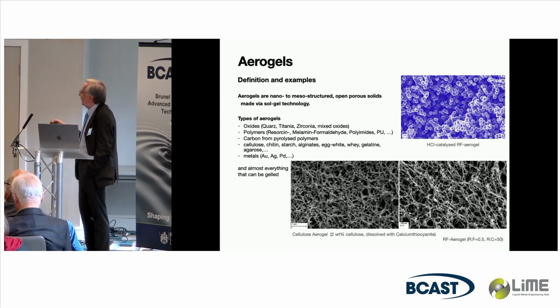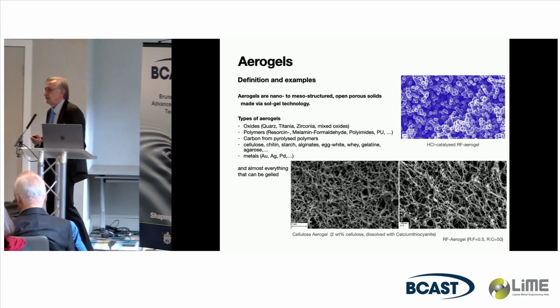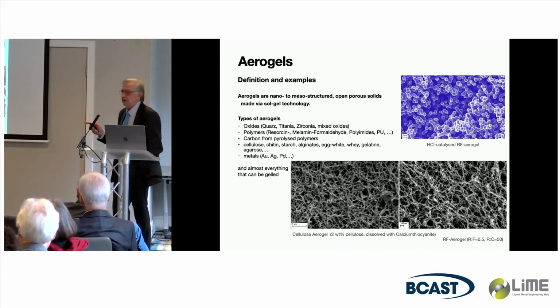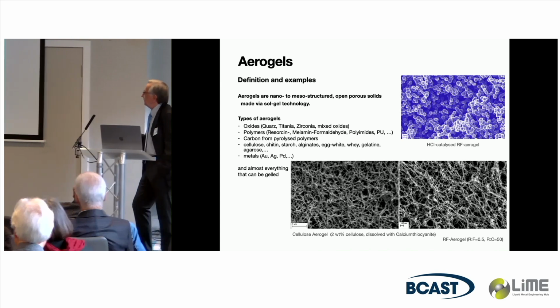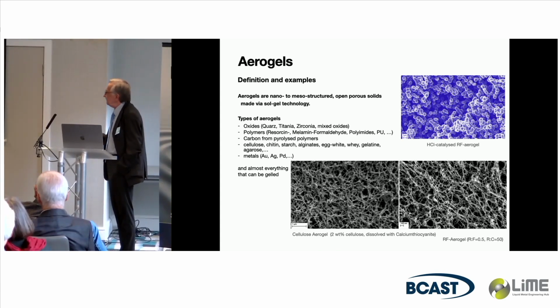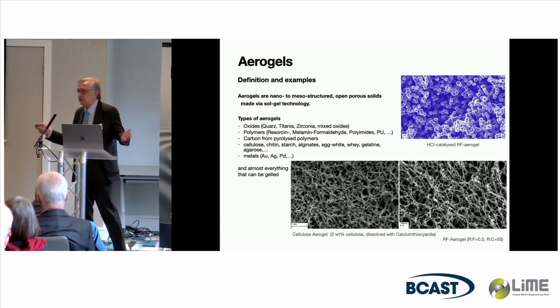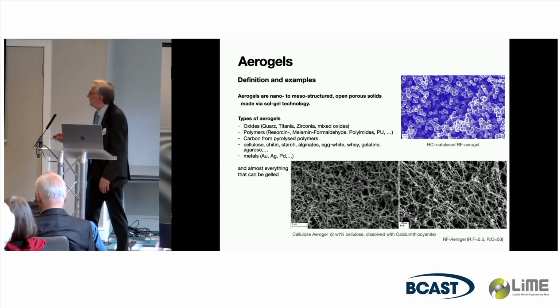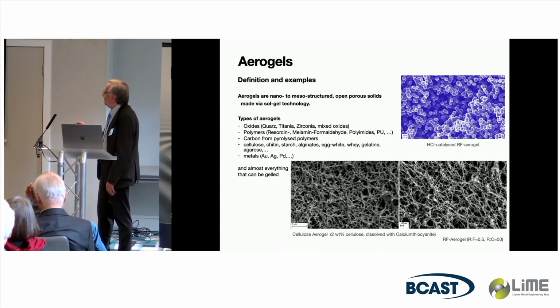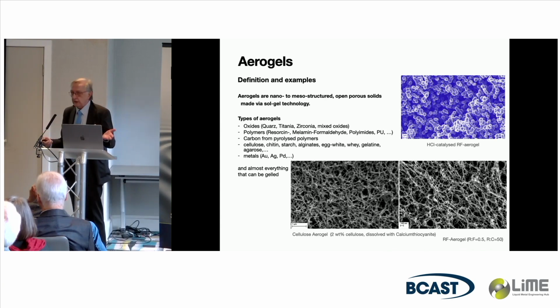Aerogels are open nano to mesoporous structures, open porous solids, always open porous, and they're all made via a sol-gel technology. You can make aerogels from anything that gels. Most famous are, of course, silica, but titania, zirconia, mixed oxide, silicon oxycarbide, silicon carbide, everything is possible. Polymers, of course, resorcinol formaldehyde, polyimides, polyurethanes. You can always carbonize them to get carbon aerogels.